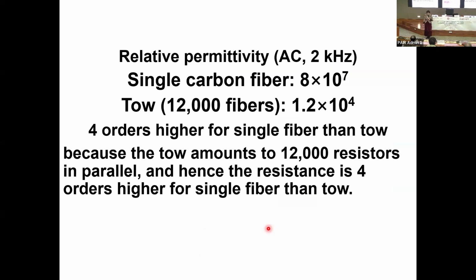So we measured the relative permittivity, AC, for single carbon fiber is 8 times 10 to the 7. For the tow, it's lower by 4 orders of magnitude, 1.2 times 10 to the 4. So 4 orders higher for single fiber than the tow. And that is because the tow amounts to 12,000 resistors in parallel, and hence the resistance is 4 orders higher for the single fiber than the tow. And a high resistance helps the establishing of a high electric field needed for that sucking.